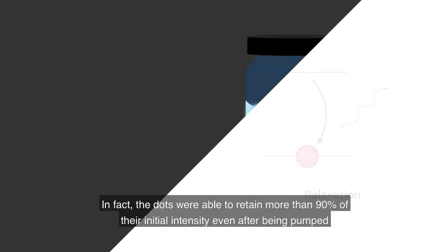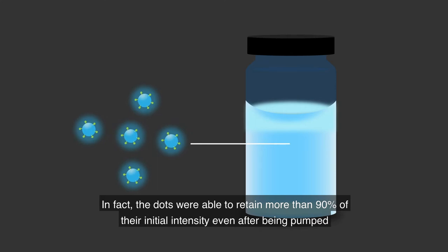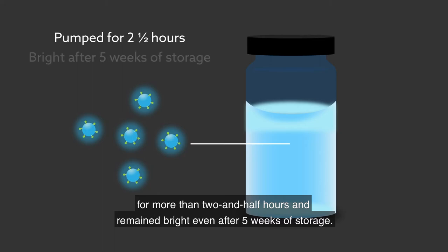In fact, the dots were able to retain more than 90% of their initial intensity even after being pumped for more than 2.5 hours and remain bright even after 5 weeks of storage.